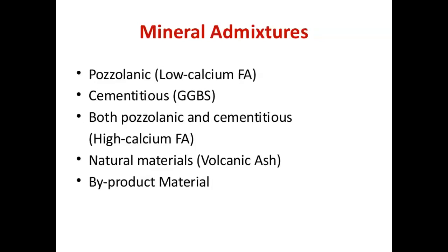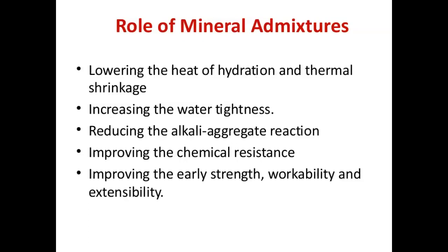So what are these mineral admixtures doing? They lower the heat of hydration and thermal shrinkage. How it lowers the heat of hydration is, for example, when you take fly ash, the fly ash doesn't have any cementitious property at all. So for example, I am using 70% cement and 30% fly ash. First, the 70% cement will be mixed with water and will get hydrated. Whatever water we add will be utilized by the 70% cement for the hydration process. After hydration, CH and CSH are formed. Once CH, that is calcium hydroxide, is formed, the fly ash will start reacting, called the pozzolanic reaction or secondary reaction, with this CH and try to convert it into CSH.